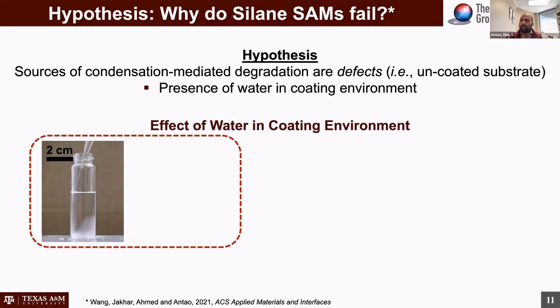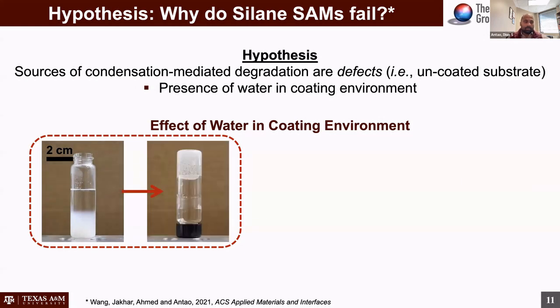The first one, I'm hoping this video plays. It wasn't playing during the practice run. So, okay, it is. We took a vial of water and we put some silane into the water, and then we waited to see what will happen. And what we observed was, after less than 5 minutes, you form this silica aerogel in essence. The silane has basically hydrolyzed and cross-linked in the presence of water, and bonded to itself. And so you form this agglomerate in a sense. This is a fairly large scale process because we wanted to observe it on the macro scale. But we believe something similar happens when you have dissolved water in your solvents during your silane preparation process.